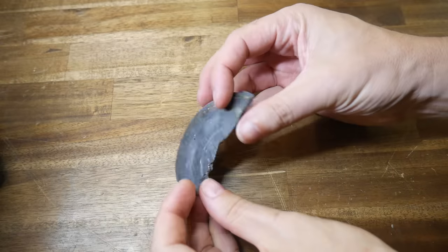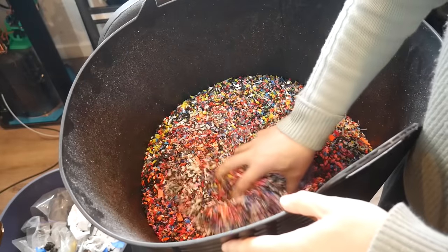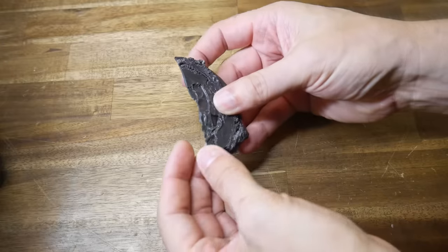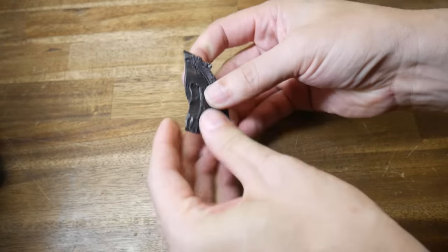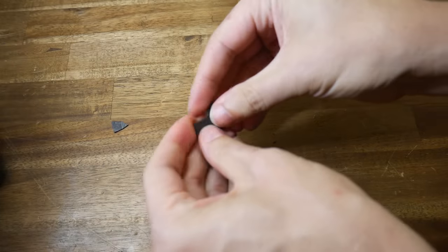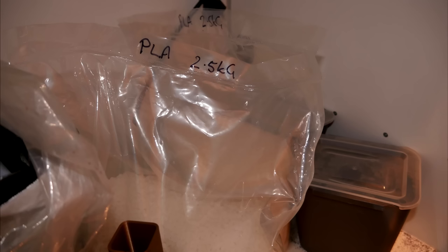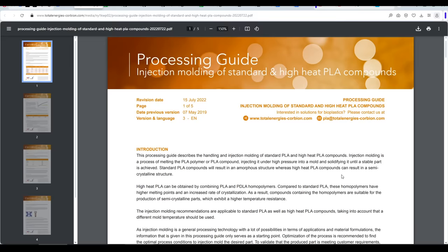At this point, I started thinking more about the material I was using. This was PLA that had already been heated up and printed before being ground back down into small chunks where it had been sitting in this bucket for years now. Whether it's the repeated heat cycles or the absorption of moisture, this PLA was incredibly brittle. And I had some virgin PLA pellets that I could have mixed in, but I'd rather save that for filament making. I shared my frustrations with my patrons and in response, Derek found this injection molding guide for PLA.